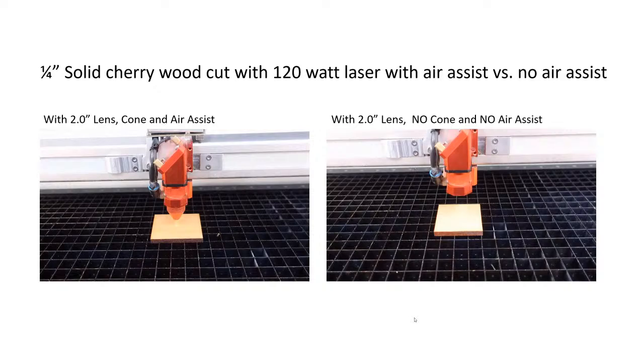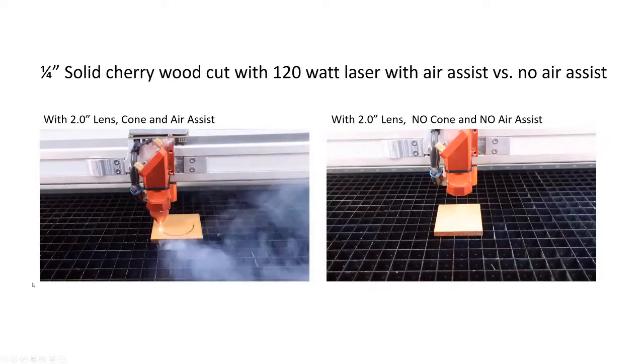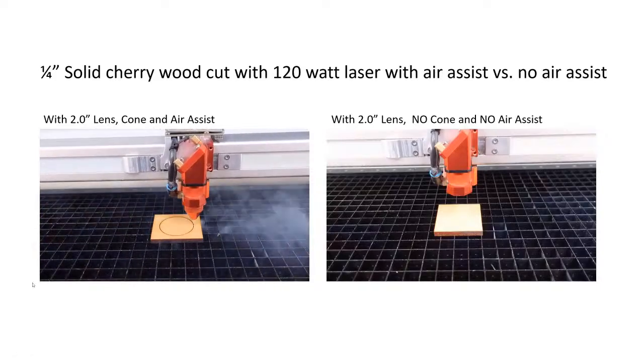So here is the difference too, if you're cutting thicker material. This is a good example of why air assist is necessary. I have a little video here. If I click and cut with a 2-inch lens with a cone using air assist, you can see the difference here. I get a nice, clean, precise cut through the eighth, or in this case, it's a 1/4-inch or 6-millimeter thick piece of cherry wood.